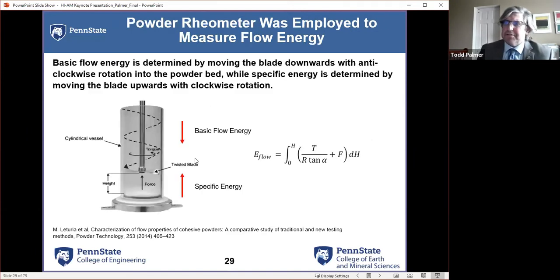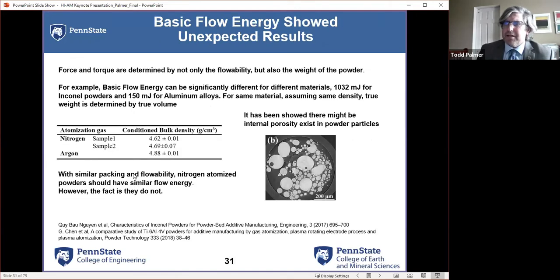I'll jump back, and don't worry, I do this to my students all the time. So how is this measurement being made? I'm looking at a blade and I'm pushing powder with this blade. So one of the things that's going to go into this type of measurement is the mass of that powder in front of the blade. So a couple of my students started looking at some other powders, and this is a cross section. If you really start looking at powders, you're going to start seeing that they are not as dense as we would hope. A lot of them have porosity in them. And so that porosity, even though it has a certain volume, means its mass is actually lower. So the density and these numbers that have gone into some of these calculations, and really these systems are measuring very few things. They're doing a lot of calculations based off a limited number of measurements in order to come up with these different parameters.